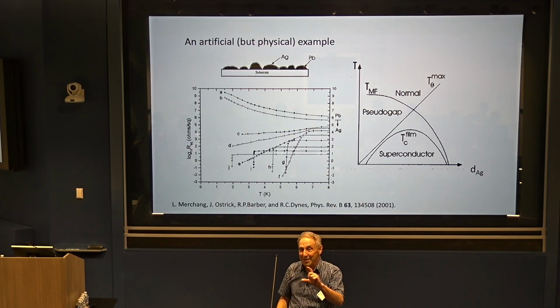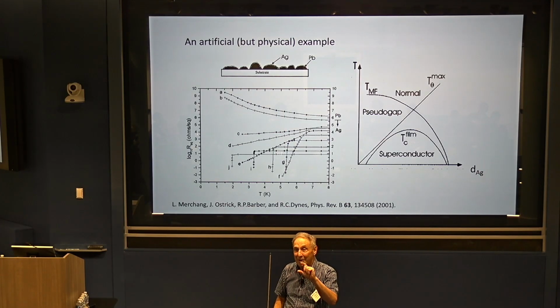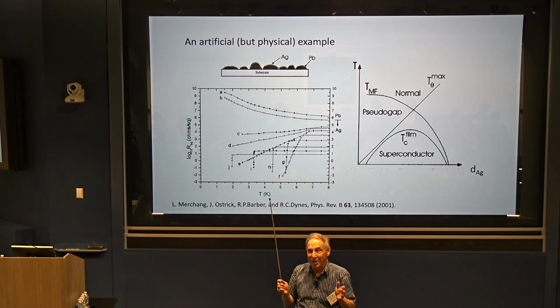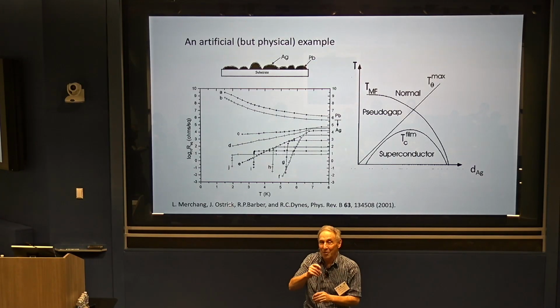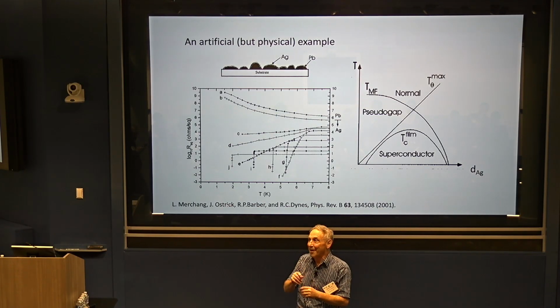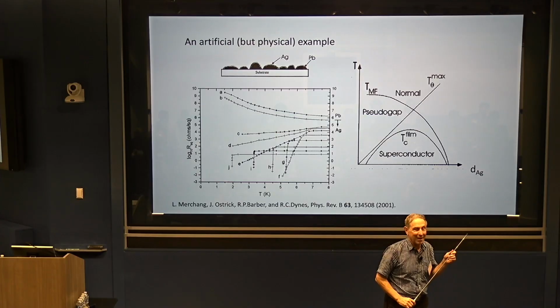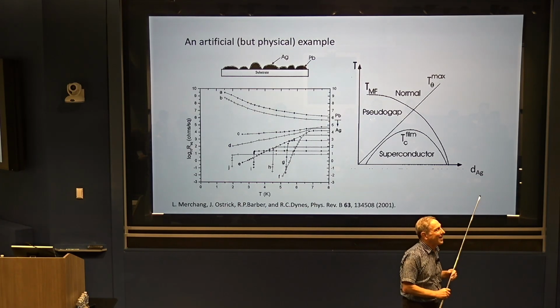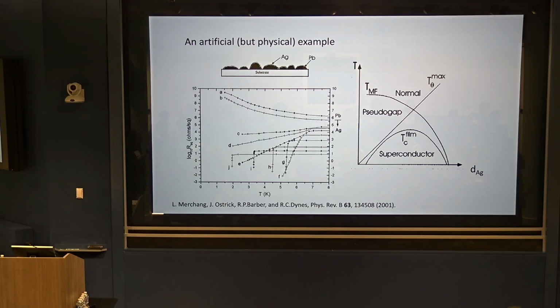But the problem is that there are many moving parts in this. We have to also put them in good proximity and ensure that we have coherent tunneling between them on a scale that's of order the gap. And if you put two dissimilar materials together, they tend to just not talk to each other. So, I mean, you're right, there could be much better choices of the metal than an overdoped cuprate. But I understand the point about raising TC while keeping large electron density, right?